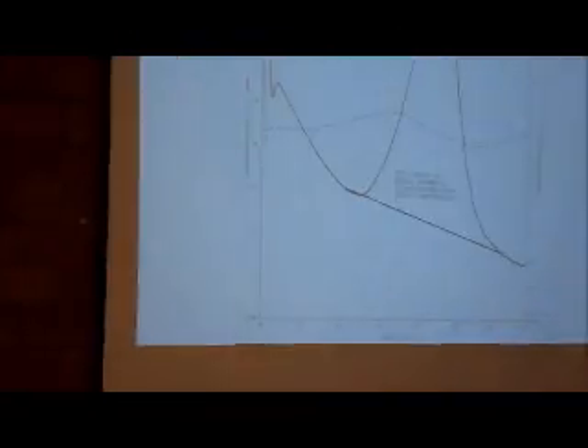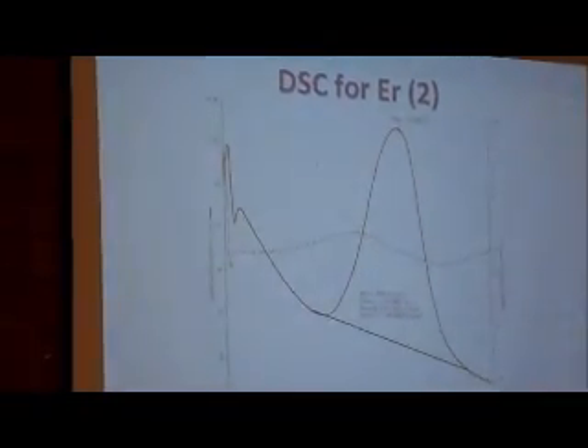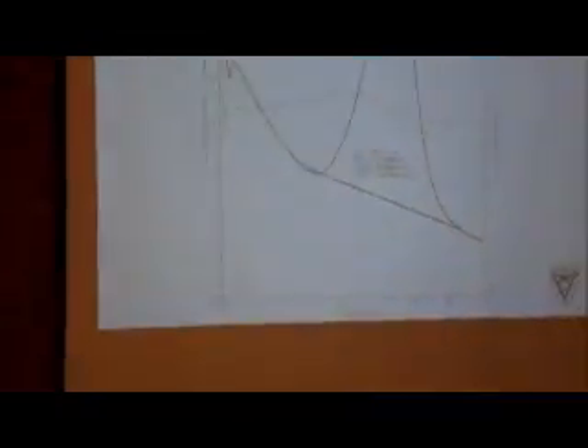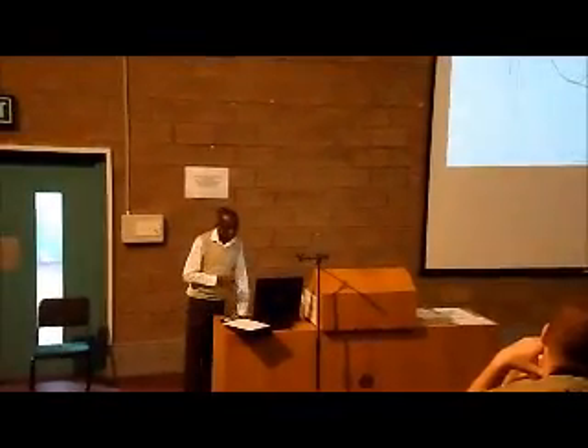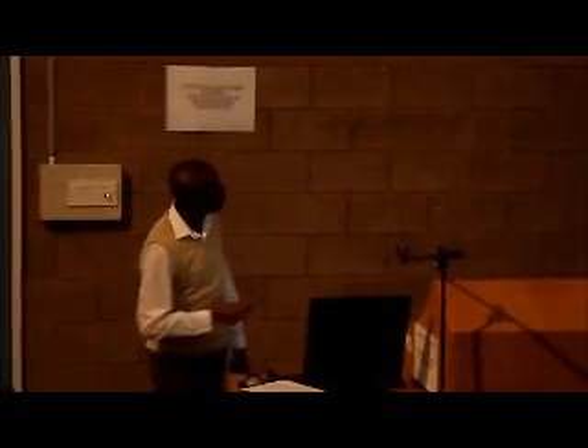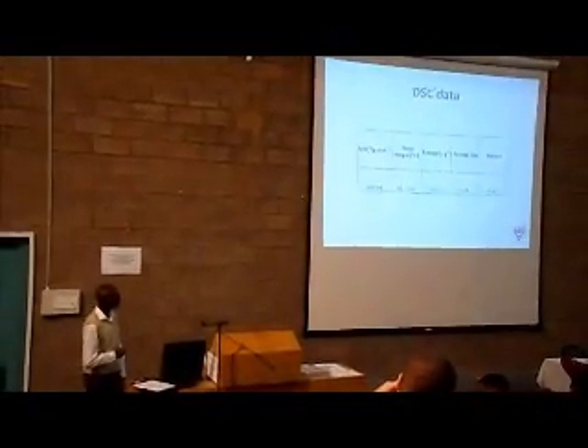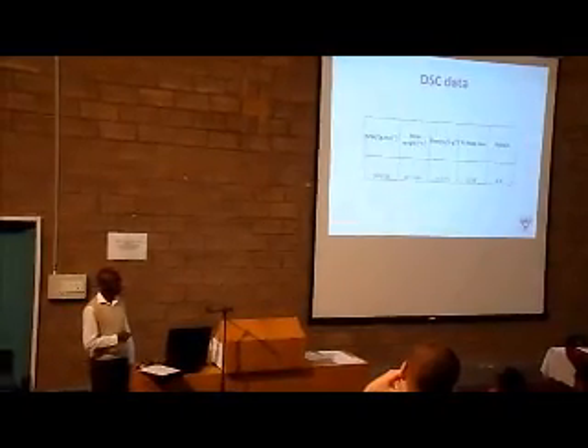Okay, so moving on to the DSC, which is the differential scanning calorimetry. This was done up to 250 degrees, but I just showed up to 180 degrees. We can see here that this is an endothermic peak showing the loss of water. The area underneath is equivalent to a specific amount of energy, and it's just to show that there was a specific water loss stage at that point. And then this data just characterizes that particular peak to show that at that stage we lost approximately 8.8 waters, and that corresponded to a mass loss of roughly 9.68, in a temperature range of 82 to 166 degrees.